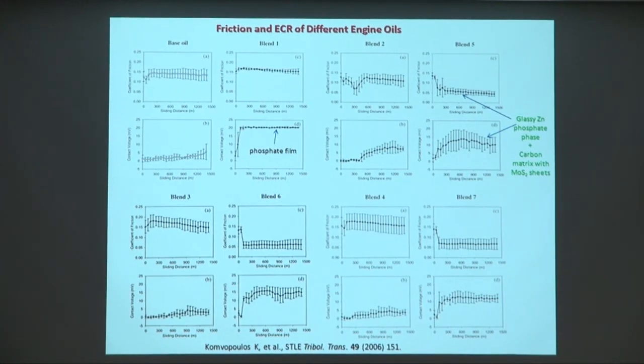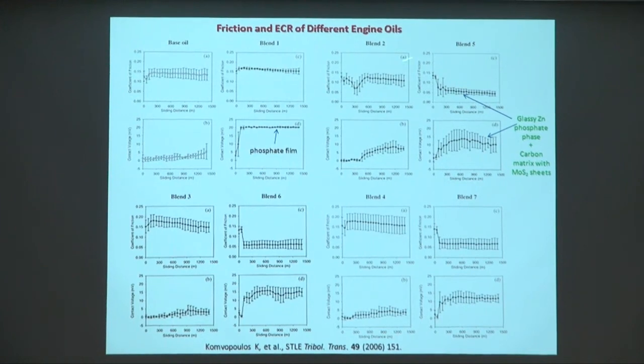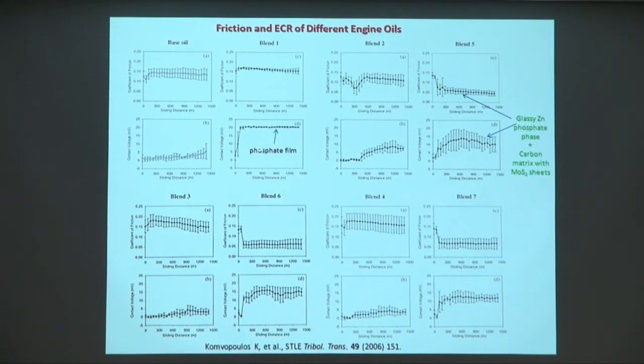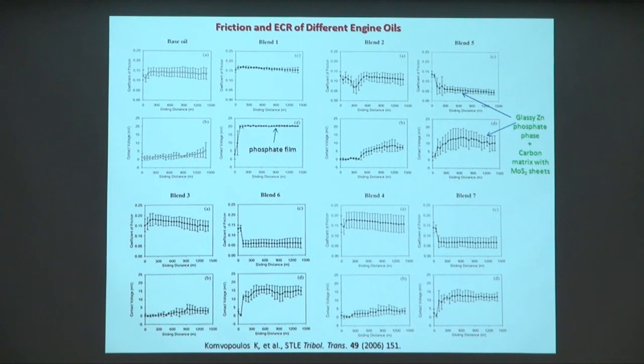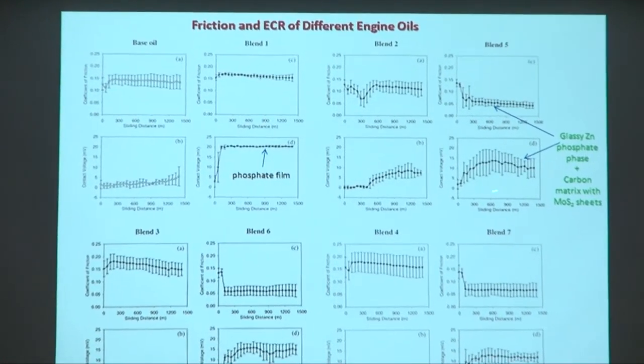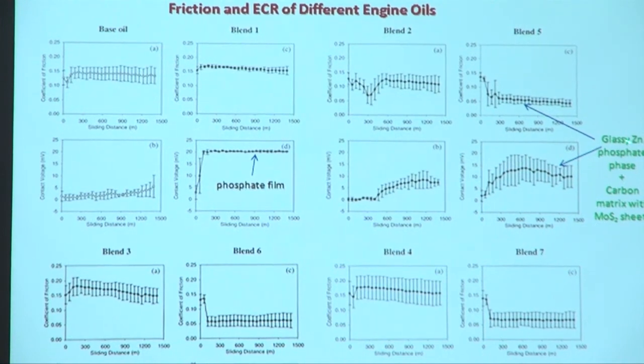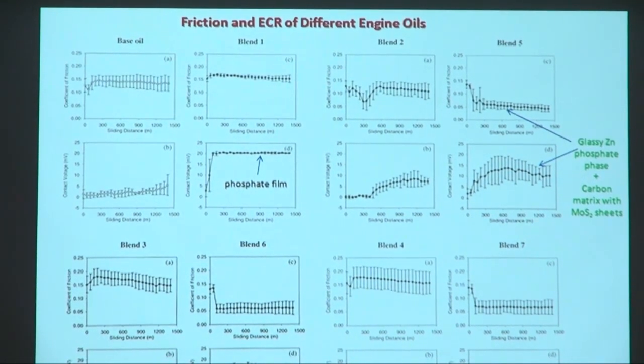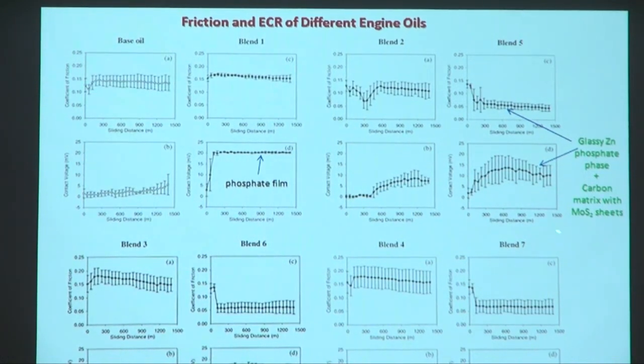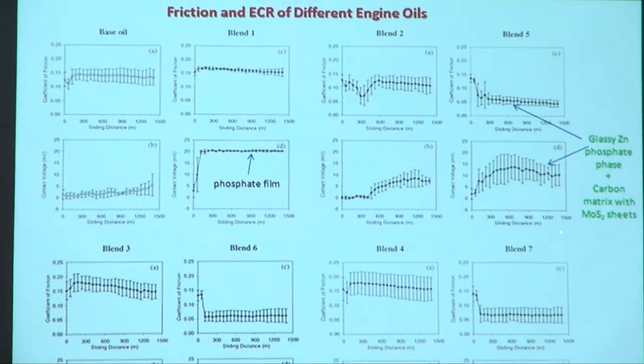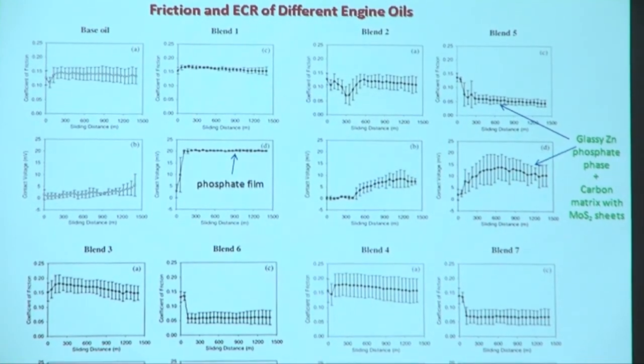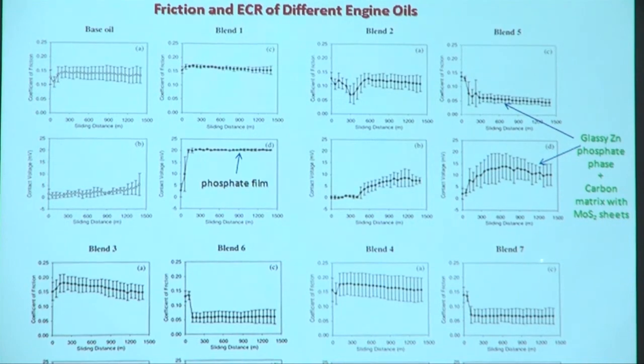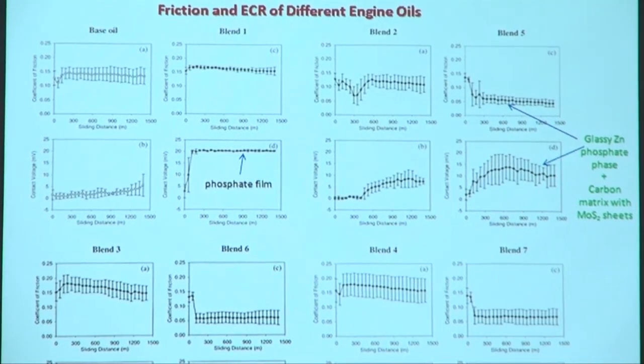So this is a busy slide, of course, but it's comparing base oil blend 1, 2, 3, 4, 5, 6, 7, and so forth. I'm drawing your attention here that the film is forming as the contact voltage indicates. That's a phosphate film. And here as well, this is the blend that has the ZDDP and molybdenum, so we can form hard phases that are glassy in nature because of the presence of phosphorus and zinc, and soft phases like molybdenum disulfide because of the molybdenum contents that is known to be a solid film that lubricates the surfaces.